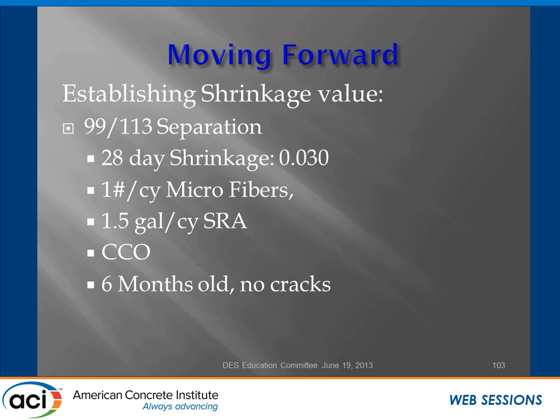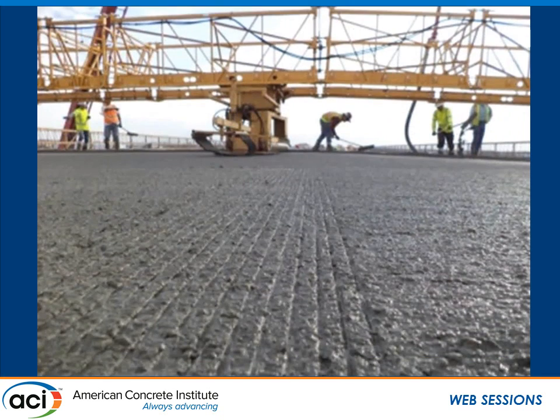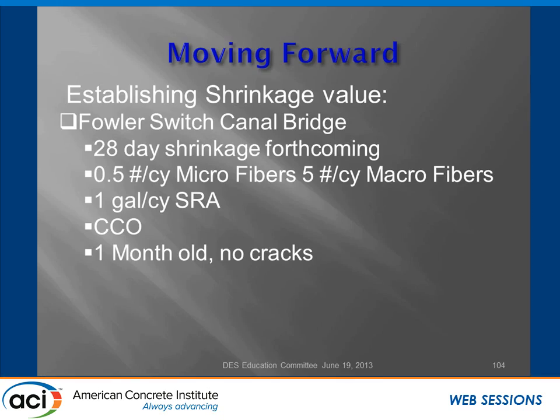We've done some more projects here that weren't mentioned yet. This is the most recent, 99113, which had a 28-day shrinkage of 0.03. It had 1 pound a cubic yard of microfibers in it. They did that with a gallon and a half of SRA. This was done by a change order. It's 6 months old now, no cracks. There it is. But there's one data point for us, 0.03.